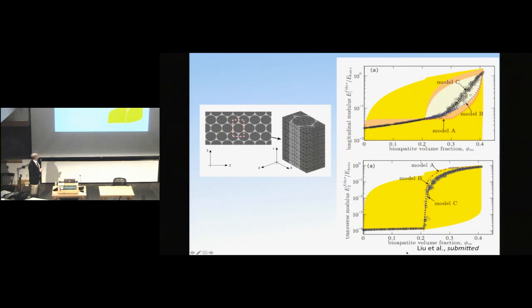And we're actually including a little bit of structural information in here, which is different on the two sides. But just pay attention to the orange envelope. And again, we follow something close to the lower bound until a critical point. So this critical point where this response shoots up from this lower bound all the way up to the upper bound very rapidly is called the percolation threshold. And this is where a continuous network of mineral begins to form on the exterior of these fibrils. This is just a simple numerical model, where all this gray intrafibrillar space forms a truss of mineral.